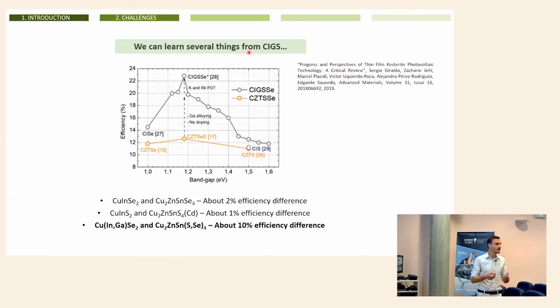And why do we think this is the solution or can really have a high impact on kesterite? Because if we take a look at the close cousin copper indium gallium diselenide, time ago, CZTS was at 12–13% efficiency. And the jump in efficiency was thanks to two processes developed for CZTS. So if we take a look at the copper indium diselenide and kesterite with band gap around 1 electron volt, efficiencies are not so different. The same for 1.5.